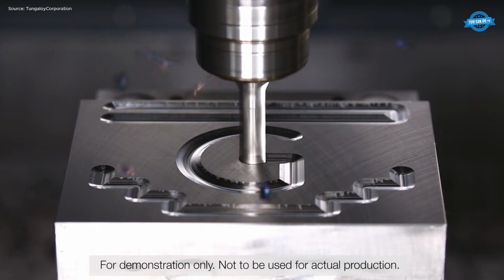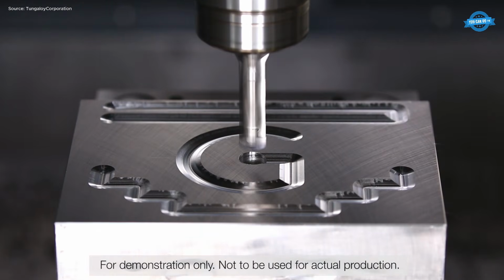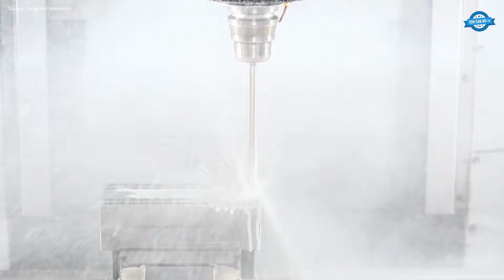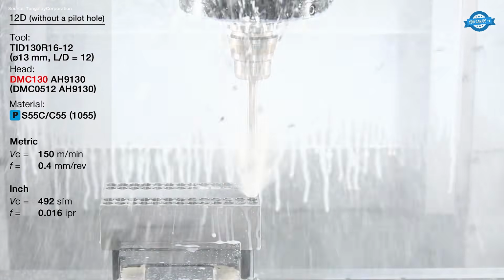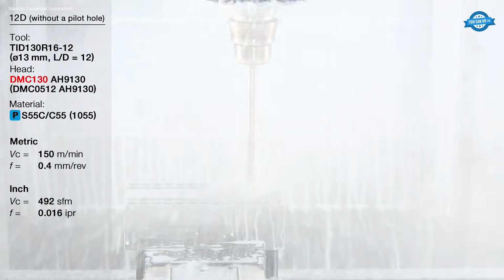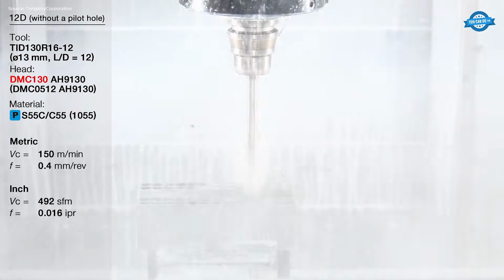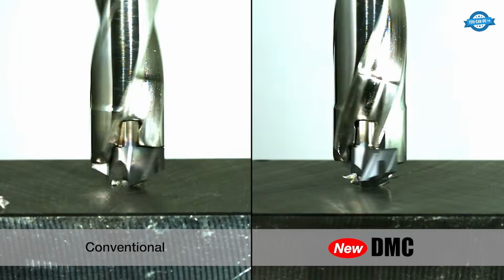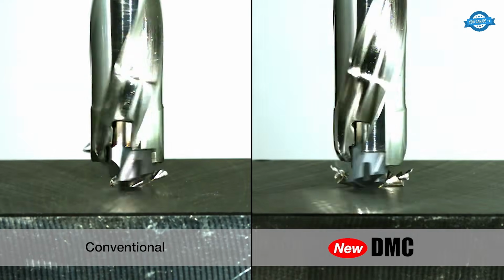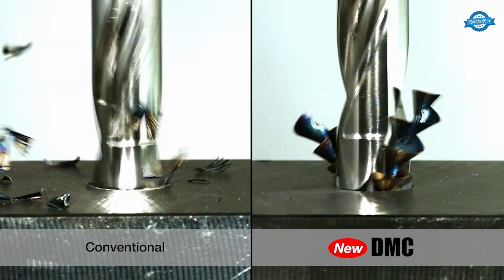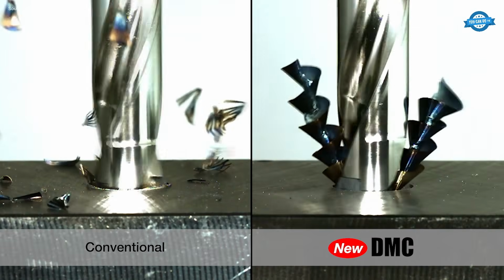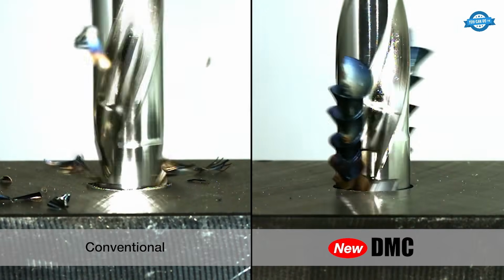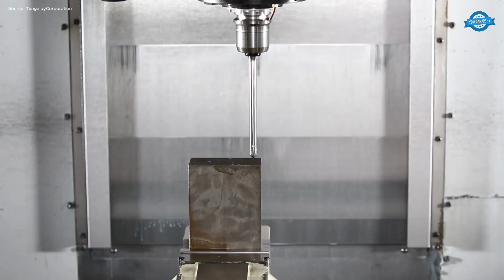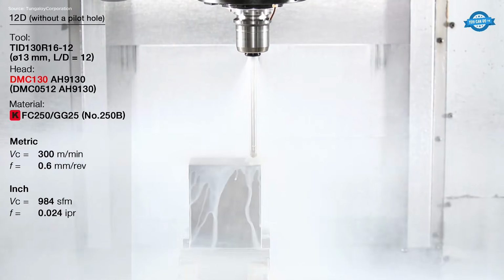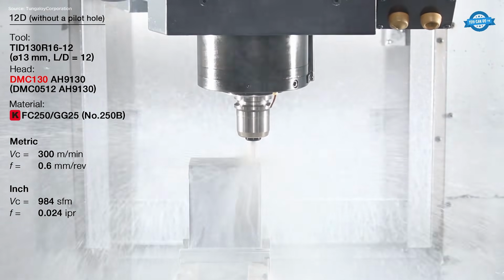The DMC drill head features a double margin and quick centering geometry, allowing stable, accurate drilling even at 12x depth without a pilot hole. Ideal for materials like S55C and GG25, it achieves cutting speeds up to 300 meters per minute and feed rates up to 0.6 millimeters/rev, outperforming conventional solid drills in both speed and durability.